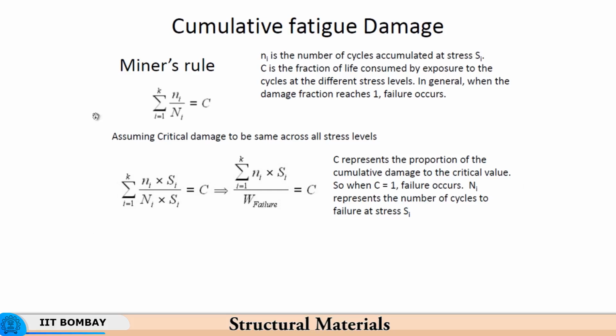So, fatigue damage keeps accumulating, and over many cycles of fatigue you have accumulated damage. If you look at this fraction, which is essentially the Miner's rule, small ni is the number of cycles subjected to under one stress condition, and capital Ni is the fatigue life under that much amount of stress. So, capital Ni is the fatigue life in number of cycles at stress Si, whereas small ni is the actual number of cycles to which the workpiece was subjected at the stress Si.